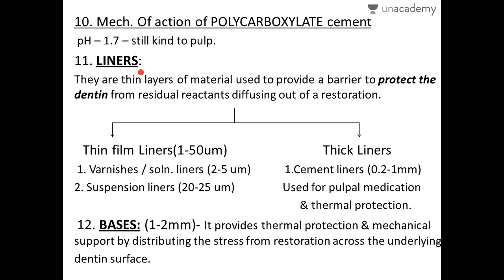Liners are thin layers of material used to provide a barrier to protect the dentine from residual reactants diffusing out of a restoration. Restorations can sometimes release products harmful to the tooth, and liners protect the dentine from these. Liners can be thin film liners ranging from 1 to 50 micrometers — including solution liners like varnishes (2–5 µm) and suspension liners (20–25 µm).